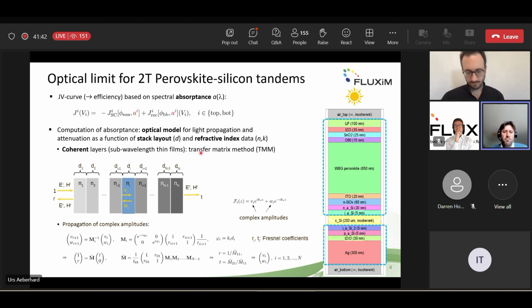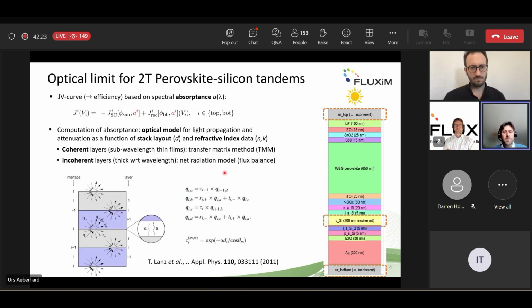Now the optical model, how it is chosen depends on whether you have thin film layers or incoherent thick bulk components. For the thin films, and you have a lot of thin films in your stack, including the perovskite, the standard model is the transfer matrix method, where you propagate the complex amplitudes of plane waves through a stack using the Fresnel coefficients at the interfaces between materials with different refractive indices. If you have, like we do in this case, also incoherent thick layers where the light loses coherence, so you have some part that is much larger than the wavelength of the light,